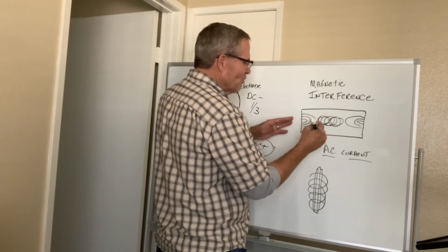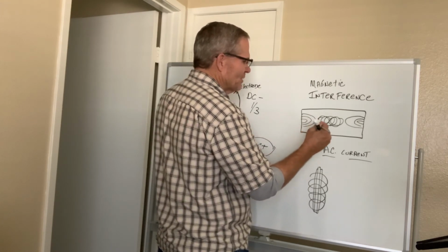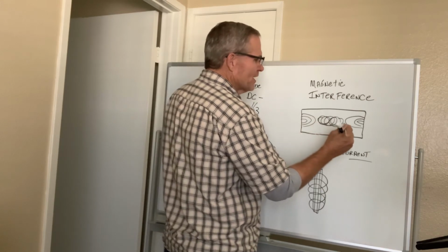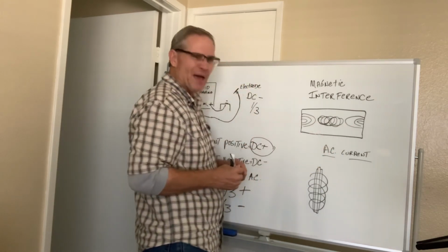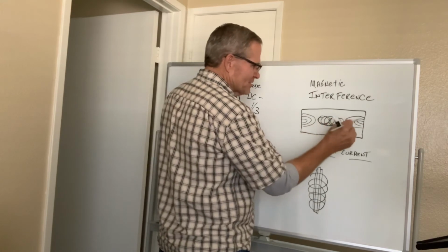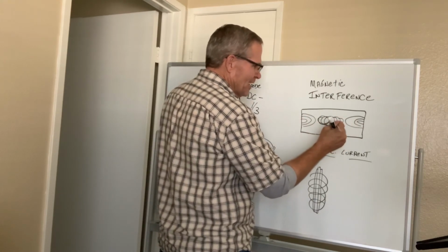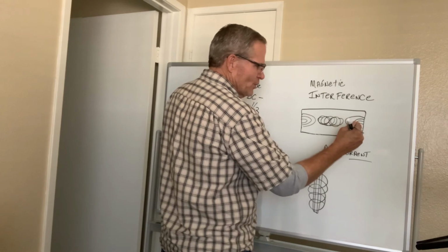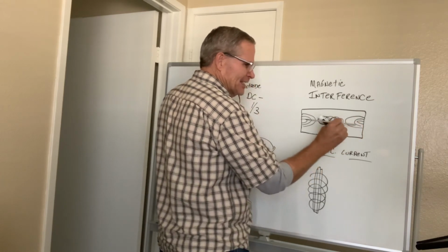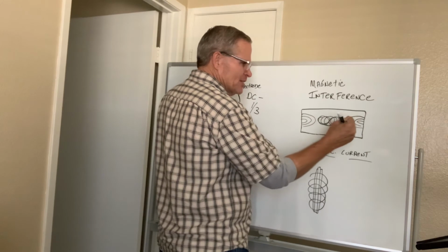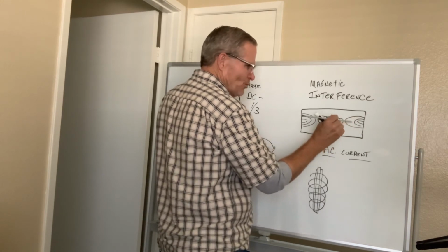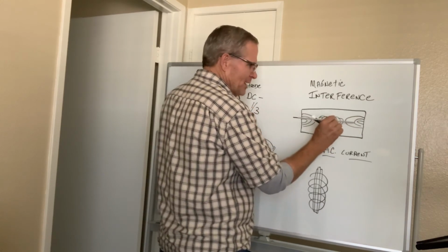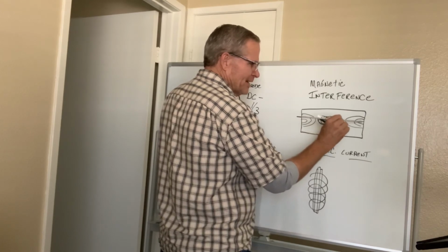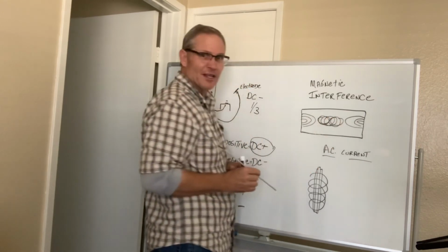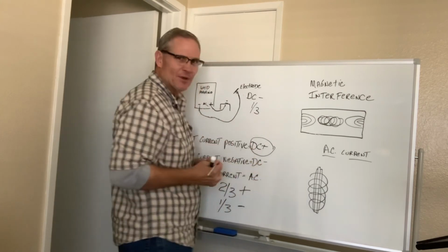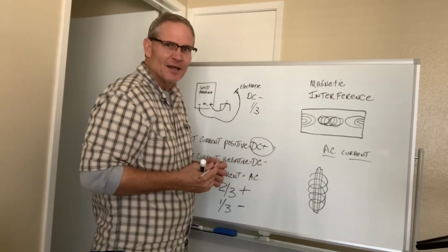You don't get much magnetic interference in the beginning. However, when you get towards the end of the weld, that's where it really becomes more magnified. This is much more magnified than the beginning of it. As you get towards the end of the weld, you would bring the electrode in towards the plate, in towards your body, if you will, the head of this towards me, in order to control that magnetic arc flow towards the end of the plate. And that's a very, very common way to offset that.